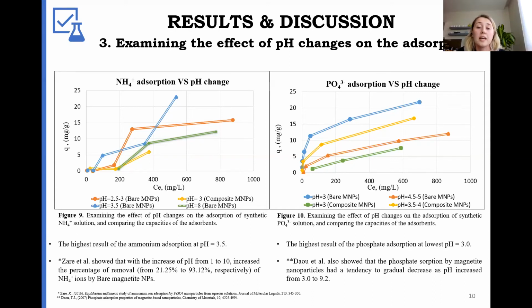But by the way, our expectation at first was to obtain the highest adsorbed ammonium ions when the pH was 8. Ammonium adsorption on bare magnetic nanoparticles was studied by Zare et al. Their results show that with the increase of the pH from 1 to 10, the percentage of removable ammonium ions by the adsorbent was increased from 20 to 90 respectively.